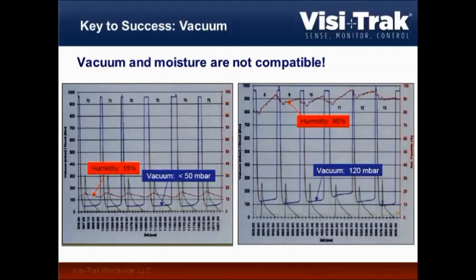Now, vacuum and moisture, we know that is certainly not compatible, and a lot of moisture either comes from the air, so make sure the air moisture is low around the die casting machine, but most of it will definitely come from the lubricant. So what you have to make sure is that you use a micro spray and disperse it fine on the surface, and make sure it actually will evaporate before you close the die.